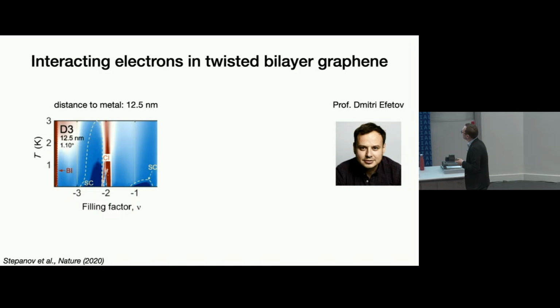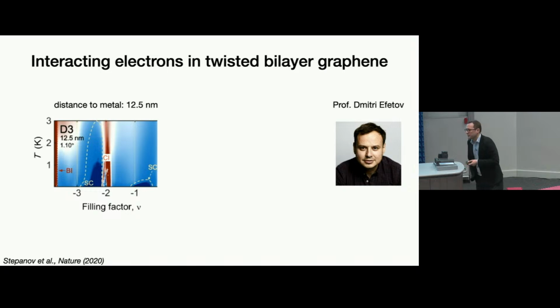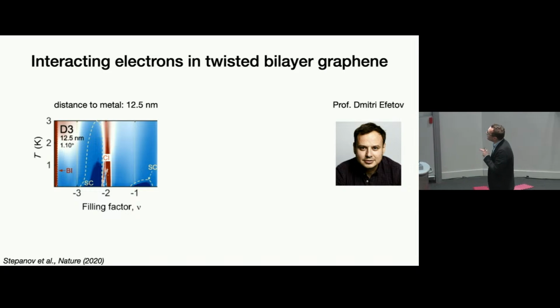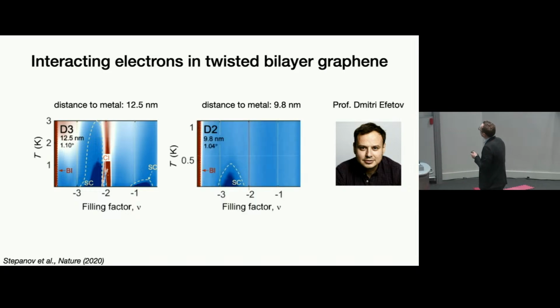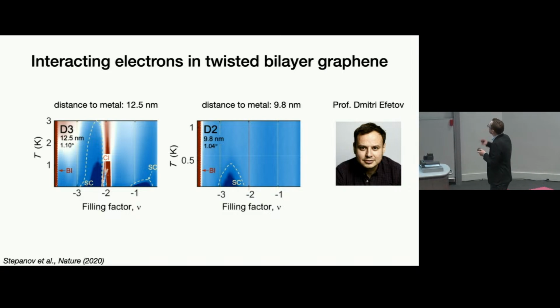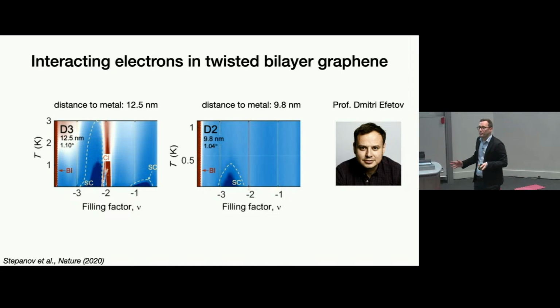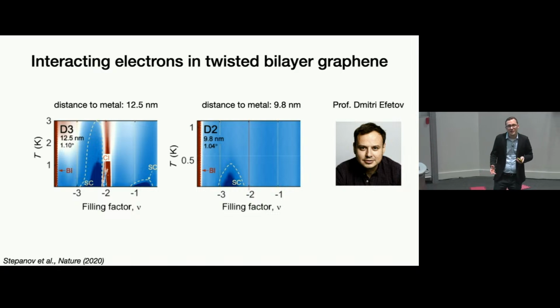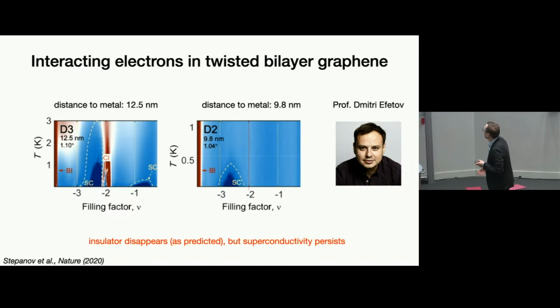So here's one of his measurements, where the distance between the graphene and the metal is only 12.5 nanometers. But this looks kind of similar to the result I've shown previously. You have your insulator in the middle, and you have the superconductors on both sides. But then when you make the metal even thinner, with a distance of less than 10 nanometers, the result looks completely different. So what has happened is the insulator has disappeared, as we had predicted. So that made us very happy.